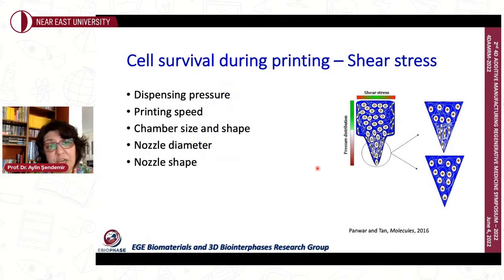So it is very much advised that you do in silico modeling of your bioprinting process, in which case the parameters: your dispensing pressure, how much pressure you're using to extrude the cells through your nozzle, your printing speed, your chamber size and chamber shape, the nozzle geometry, the diameter, the nozzle shape, again, how steep or how leveled your nozzle is. These will all change the amount of shear stress that's applied on your cells, and the pressure distribution will also change. So therefore, I do recommend you definitely include an in silico modeling of your bioprinting with the properties of your own cells and with the properties of your own bioink, so that to optimize these printing parameters to keep highest cellular viability.